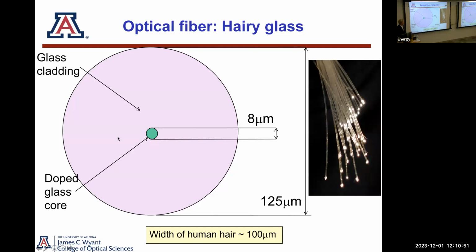So, I call it hairy glass because it's about the same diameter as human hair, optical fiber, and it has a core, and the doping is very modest. So the glass cladding is fused silica. It's SiO2. This is all generally made for the commodity fiber that we use every day, which is SiO2 in the glass cladding and germanium-doped SiO2 in the core. It's created by a vapor deposition process into a preform initially, so that it uses ultra pure starting material.